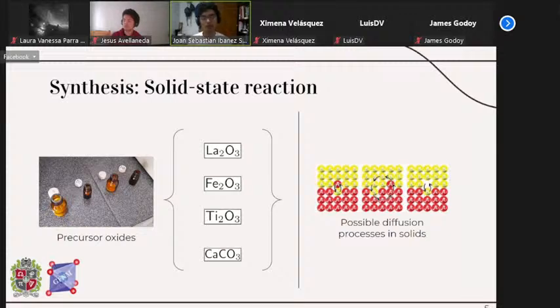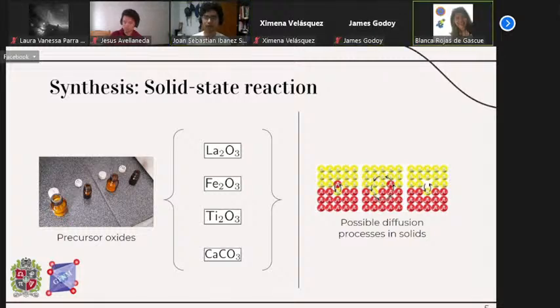They were all of them at a really high purity of at least 99.9% purity. And they were the ones that we use for our material. In particular, the solid-state reaction is a fairly straightforward method of synthesis. It occurs at high temperatures on solids and can be easily understood as a diffusion process in which the ions of each of the precursors move due to the high temperature and begin to aggregate into similarly structured oxides.